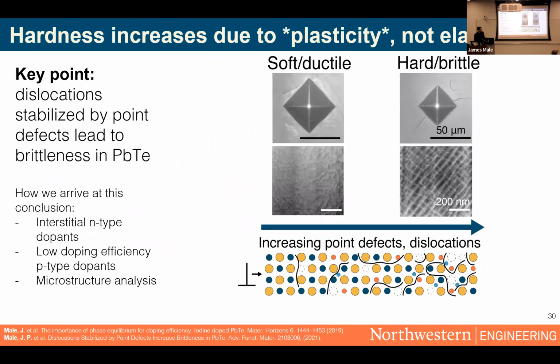So where I turned was an explanation that relies on plasticity rather than elastic bonding. I think if you came fresh out of a mechanical properties class, you would probably turn to the same explanation. So we were kind of going down a wrong path for a while, I believe. Basically, the gist of this is that adding high concentrations of certain types of point defects stops dislocations from moving through a material and makes it much more brittle.